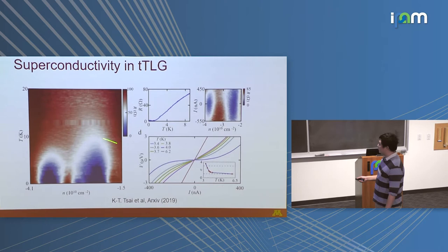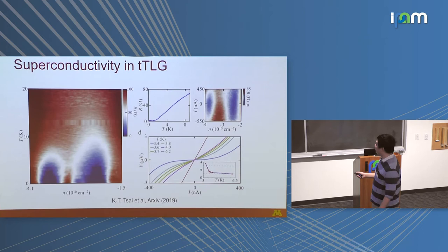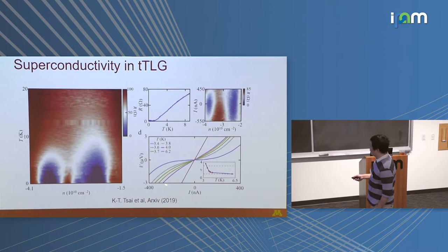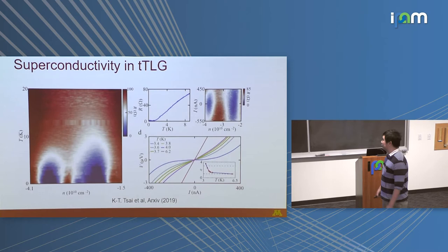We have a temperature dependence that actually goes flat, and a symmetric differential resistance against the bias. We also show it as we change temperature: the IV curve goes from linear to cubic, and it crosses the cubic around 3.4 degrees. This is the expectation you can get from a BKT transition of a disordered 2D superconductor.